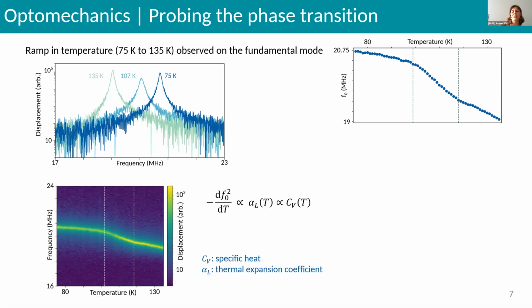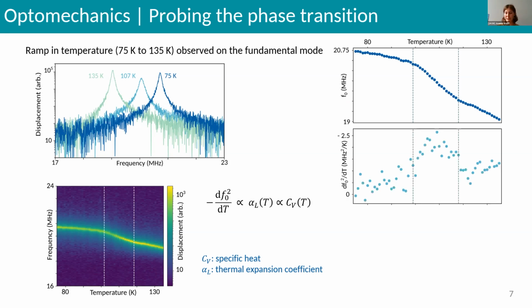The derivative of the square of the resonance frequency with respect to the temperature is in fact proportional to the thermal expansion coefficient of a material, which is also proportional to the specific heat of this material. And as we know from statistical physics, the specific heat has a discontinuity at the phase transition. So if you plot the derivative of the resonance frequency squared, you will see a discontinuity at the phase transition, which is here, and indicates the phase transition at a temperature around 109 Kelvin.